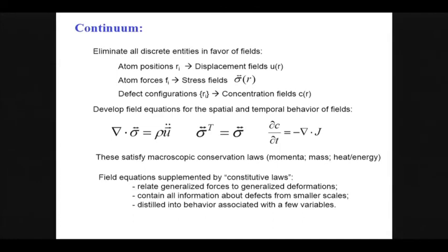But the field equations, as I mentioned, are supplemented by the constitutive laws. And the constitutive laws relate the generalized forces to the generalized deformations. And this is where all the information about everything else is, but it's all been collapsed into a few variables that exist in the constitutive law. So it's very efficient, but it relies on whatever constitutive law you used having all the information about the defects faithfully represented. And that is a trick or a difficulty.